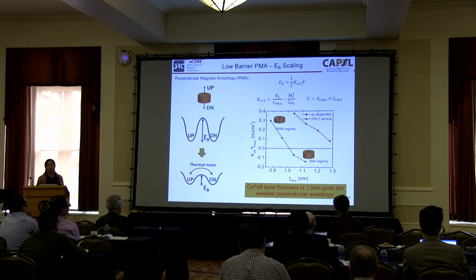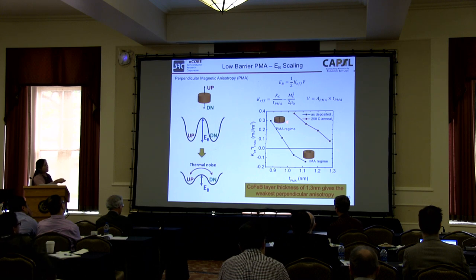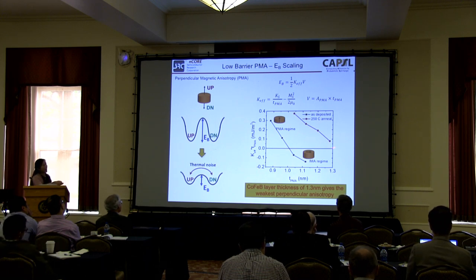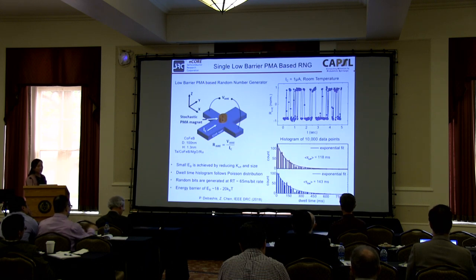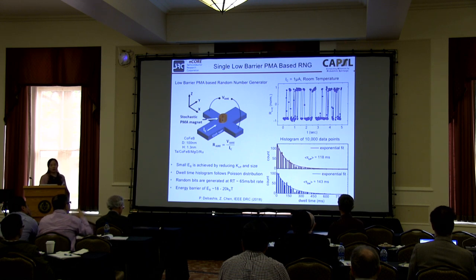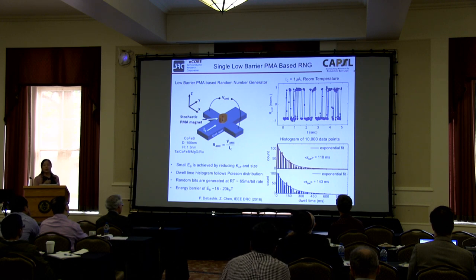And we realized that annealing and all these fabrication processing steps can impact the effective energy of our magnets. Once we picked the annealed magnets, we decided 1.3, 1.4 nanometers is roughly the sweet zone that we want to work with, where our PMA magnets can have rather small energy barriers. And as I mentioned, for the random number generator, because we have the magnetization jumping between the two states, once you guide the magnetization information out by electrical signal, these are exactly fluctuating resistance states. And these fluctuating resistance states are perfect random number generators that are used in a lot of cryptographic systems.